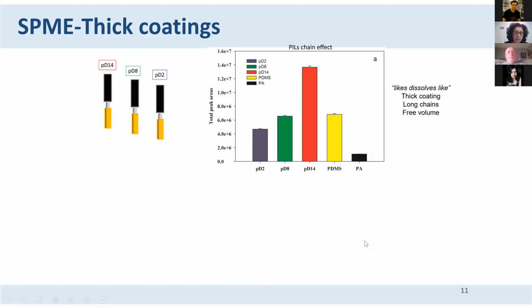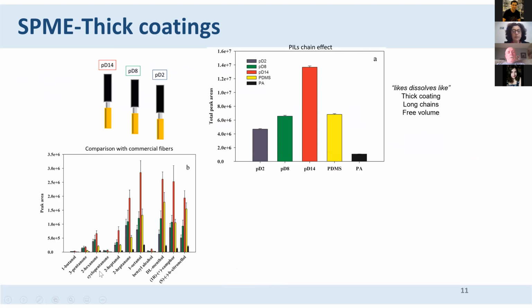And we used several compounds that you can see here, maybe polar compounds. And the total peak areas are larger for this polymer that has a chain length of 14 than for the other fibers that we prepared, including the commercial fiber. Here we can also see that for alcohols that had longer alkyl chains, the fiber with the C14 did a much better job than the others, and a much better job than the commercial polyacrylic acid fiber.